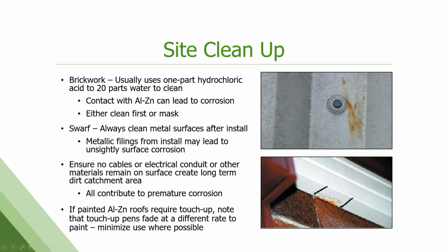Site cleanup, this is a big one, right? Brickwork usually requires 1 part hydrochloric acid to 20 parts water to clean. If you leave that in contact with the metal panels too long, it can lead to corrosion. So you want to mask off well or clean well right after. Swarf is huge. These are metal filings left either from fasteners being drilled in or cutting that's happened on site. Little metallic filings sit on the surface and then they rust and it leaves this unsightly red stain on the panel. And the complaint comes in as my panel is already failing and it's brand new. And you go, no, that's something that got on the surface that didn't get cleaned off. Once that stain sets in, it's kind of there for life, unfortunately. Want to make sure no cables or electrical conduit or other materials remain on the surface long term that could catch or hold moisture or debris.